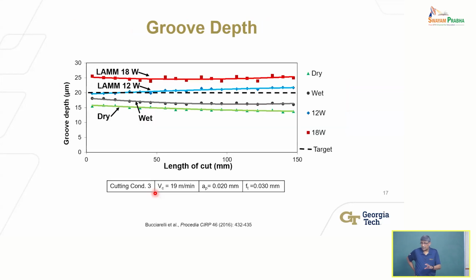This is looking at the geometry. Now looking at that cross-section, looking at the depth of the groove along the length of the groove, right? And there's a lot of information here. This is for one condition that you see here, and for the 4 cases: dry, wet, and with different laser powers. And what do you see? The nominal depth was 20 microns, 0.02 millimeters. That is what we were trying to produce.